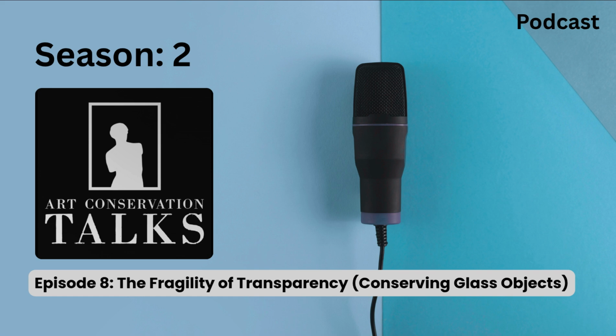Wow, what does that look like? You might see a sort of foggy or hazy appearance first. It can feel slippery or soapy to the touch. Or you might see tiny damp droplets. That's called weeping. Weeping glass. Yeah. And if it keeps going untreated, it leads to a network of fine cracks. The glass becomes opaque. That's crizzling. And often that damage is irreversible.